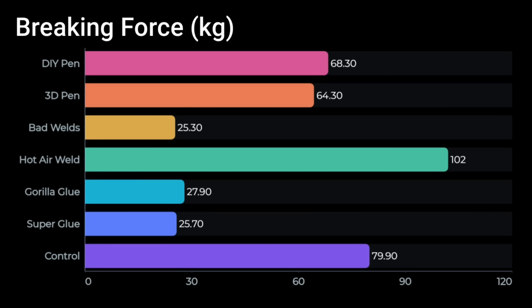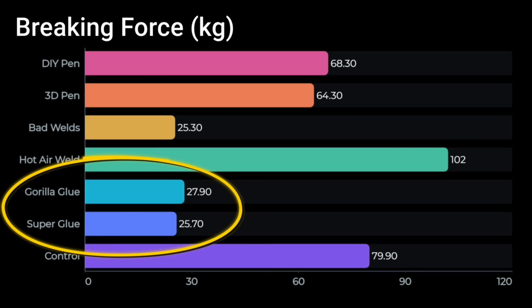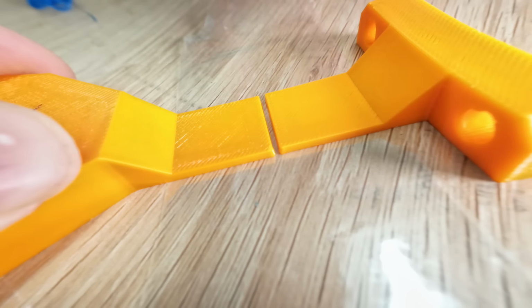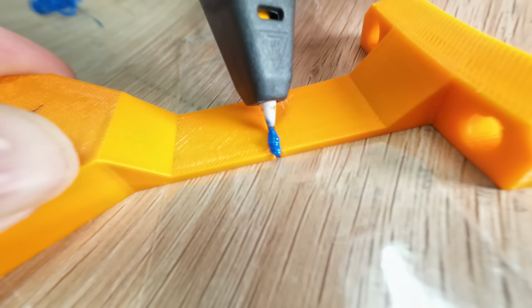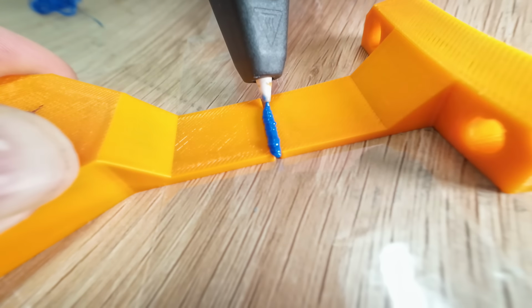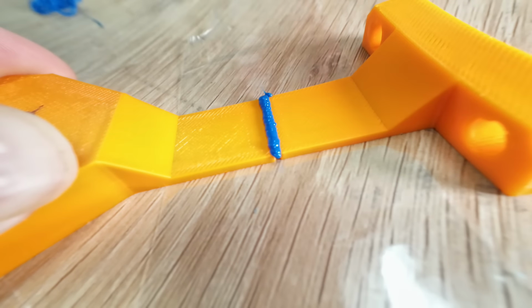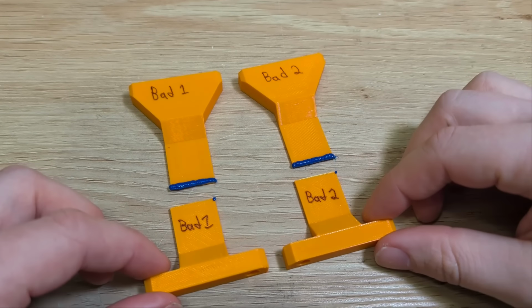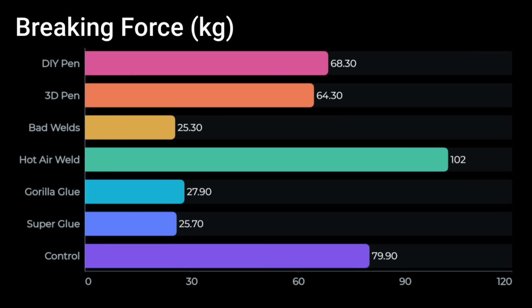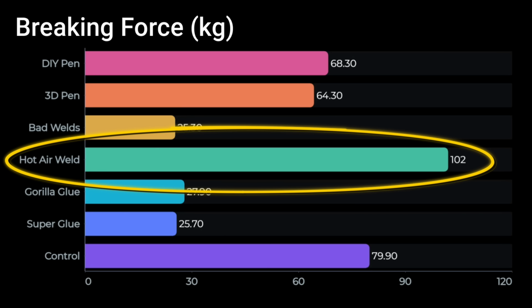One thing we can see here is that the bad weld samples were indeed bad, with a similar strength to the gluing, both super glue and our Gorilla Glue. These were the samples that we kind of just squirted the filament, the plastic, in between both samples without actually heating the base material. I have a theory as to why the hot air sample did better than the others.